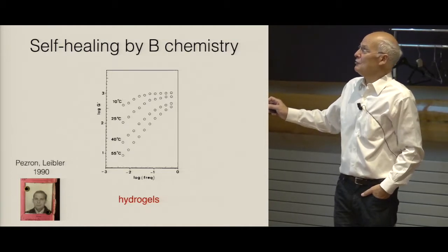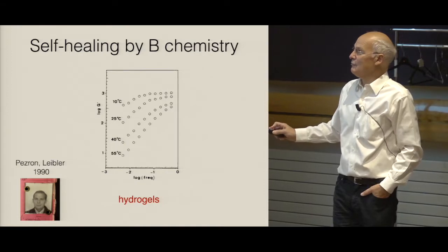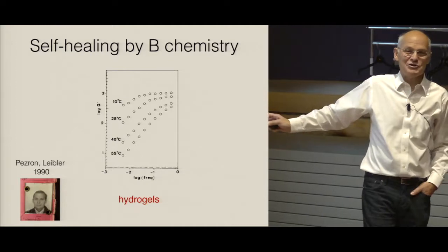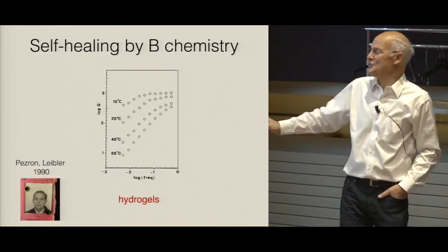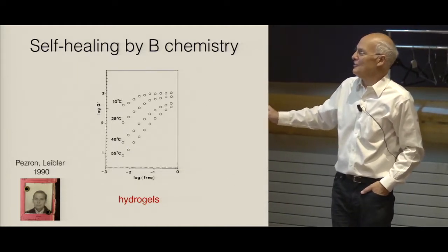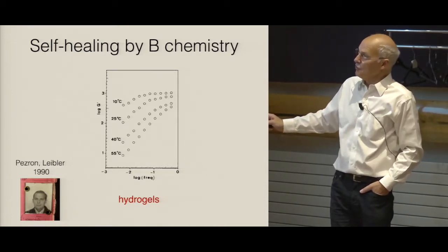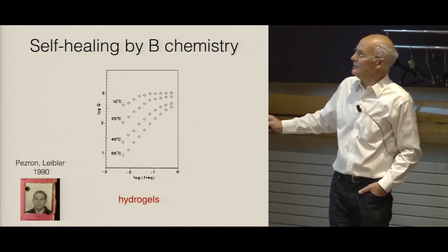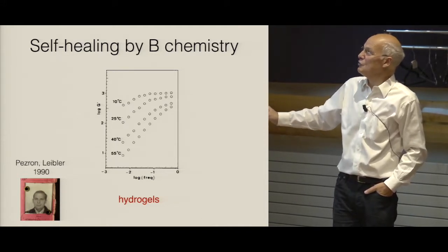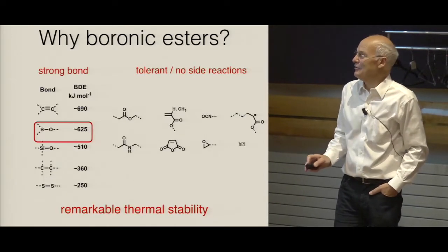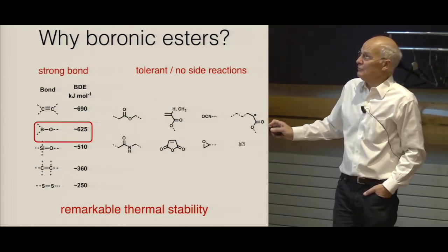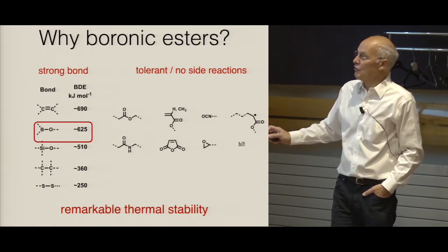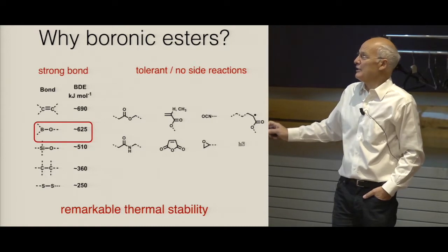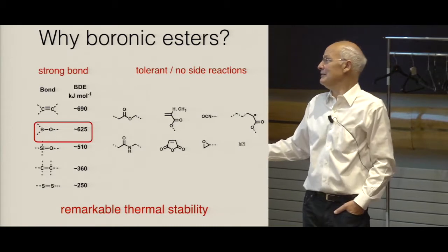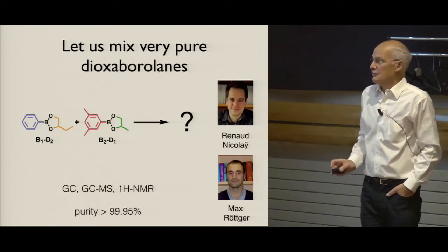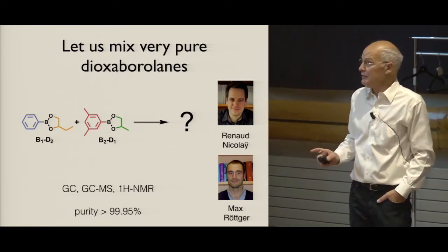So the first question: why boron? Why boronic esters? One of the answers is that when I was this age, this is my driving license, okay? And I'm not very easy to recognize, but roughly when I was this age, we made self-healing hydrogels using borate, but we didn't call it self-healing at that time, which was very bad. But we knew that boronic esters can make very rapid supramolecular chemistry. But more seriously, boronic esters make an extremely strong bond, and they are very tolerant to many chemical groups: anhydride, epoxies, acrylates, and esters. And so they are very stable chemically, and they are very stable thermally.